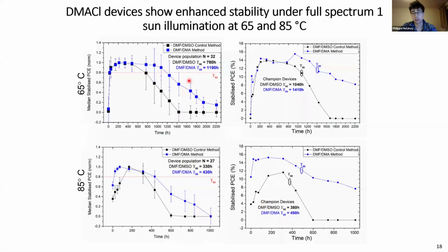So this is quite a large study. So this is just a stabilized power output. So this is an aging box, which is at 65 degrees or 85 degrees. It has a full spectrum. So this is aged with a xenon lamp. So it's a full spectrum. So it does have a UV component as well. And then we take the devices out to measure to the solar simulator and measure devices there. And then we add it back into the aging box.